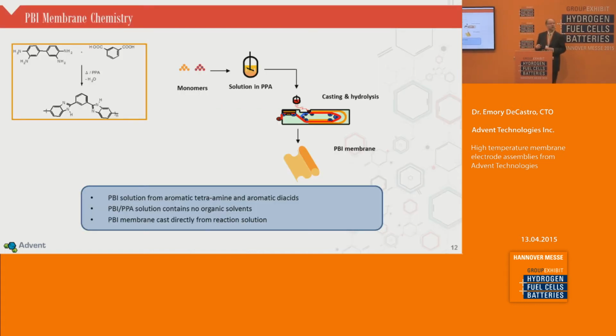Now, if we look at the other side of the coin, the PBI membrane, it really is a different beast. It's made in a different way, it has different properties. So the PBI is actually based on an imidazole, and it starts from two monomers, which are then mixed into a reactive solvent called polyphosphoric acid. You heat that solution up, you form PBI in situ, and now it's soluble in the solvent, polyphosphoric acid. You can extrude it. It's a thick, viscous solution.